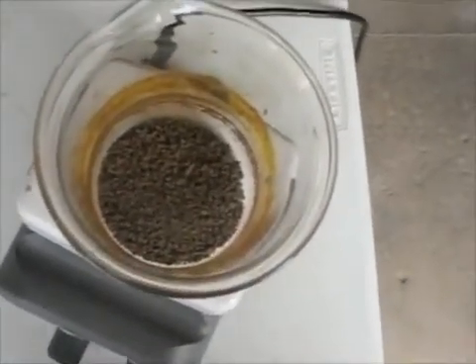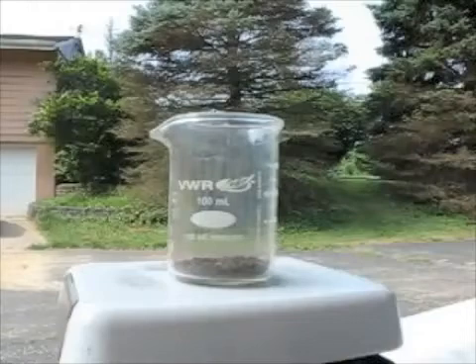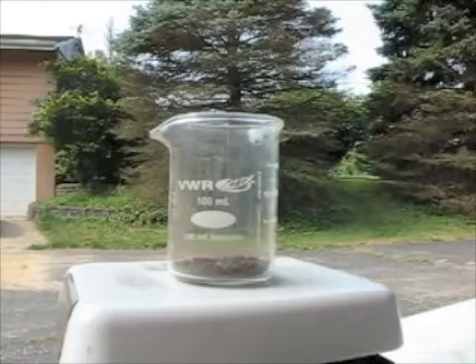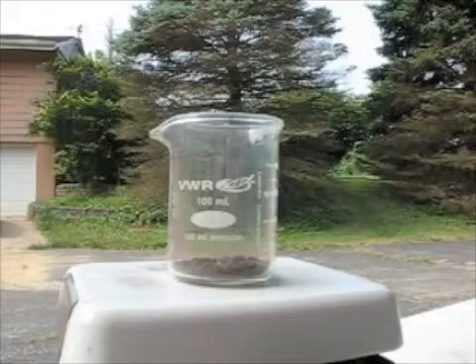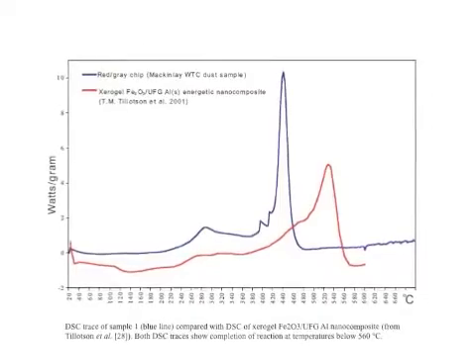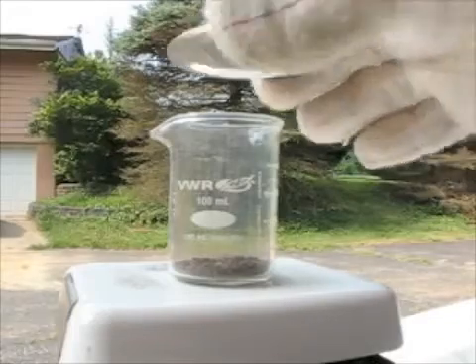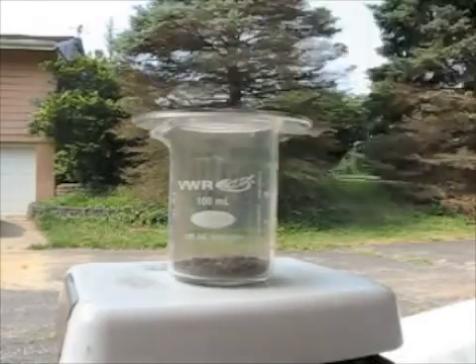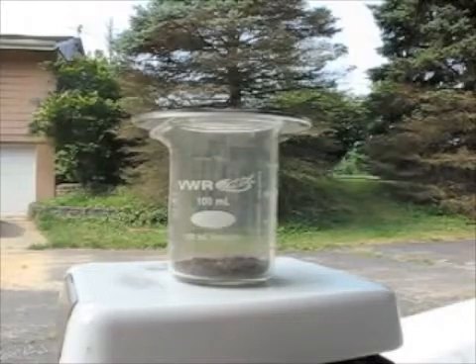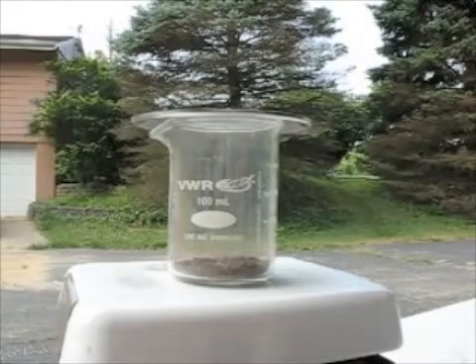For our experiment, we're going to take the hardened gel, which I've already prepared, and break it up into smaller pieces. If we take just a couple grams of this nanothermite and put it in a smaller beaker on a hot plate, and raise the hot plate to its maximum temperature of 550 degrees Celsius, this should cause the material to ignite. We'll add a loose lid to the beaker to demonstrate the pressure-volume work effects that the expanding gas should produce.